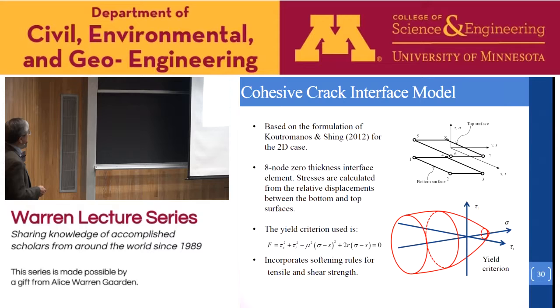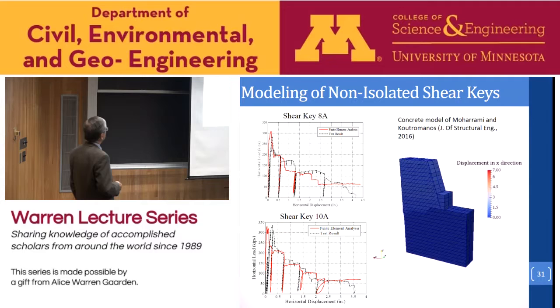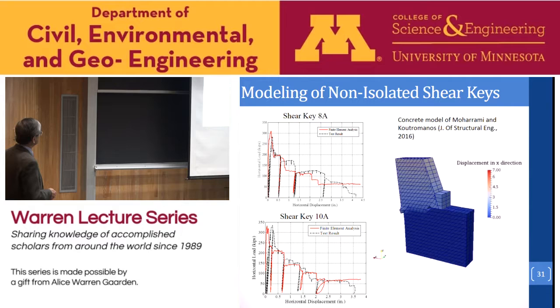And the failure is governed by a hyperboloid, okay? So this shows the shear resistance, and this is the normal stress. So this governs the mixed mode fracture condition of that interface. So now, this shows a comparison of the model with our test, so we could capture this relatively well, and also the failure behavior of the shear keys.